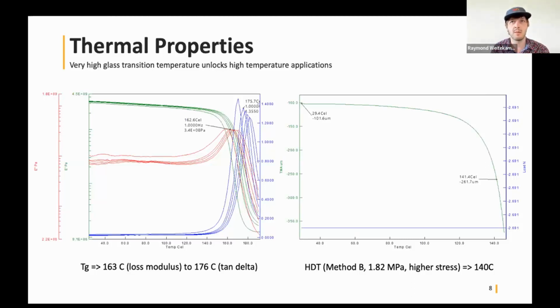And so, depending on how you want to think about working temperature, we have some customers that use our materials in applications up to 200 C. Obviously that's not going to be a load-bearing condition. That would be something like a mold insert for an injection molding process where it's getting hot and cooling relatively quickly, or a fixture on a high temp process line, like an end effector. If you're under a load, you probably want to stay under 130, but that's still hot enough to be under the hood, in an undisclosed automotive application that Corey and I will share later. We have a surprise for everyone later, and a tease to get you to come hang out with us at Rapid. But on the thermal side, it's an incredibly high working temperature.